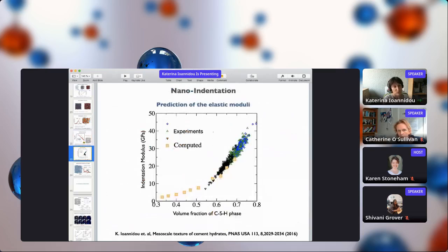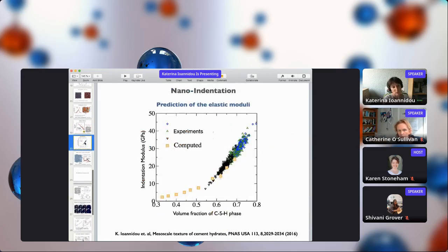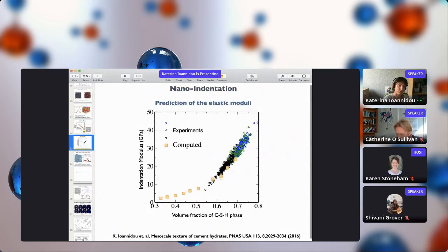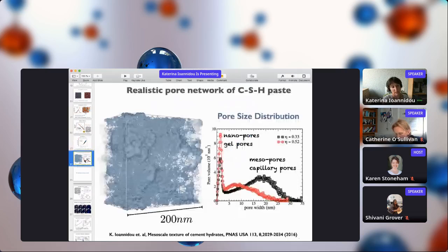The next point of validation with cement was to compute the mechanics. For example, here I give you an example of computation of the indentation modulus that we compare with experiments, and in yellow is the one computed from simulations. So we're able to compare, as I said, structure with small angle neutron scattering, nano indentation mechanics, and then next, the most important point is to compute pore size distribution.